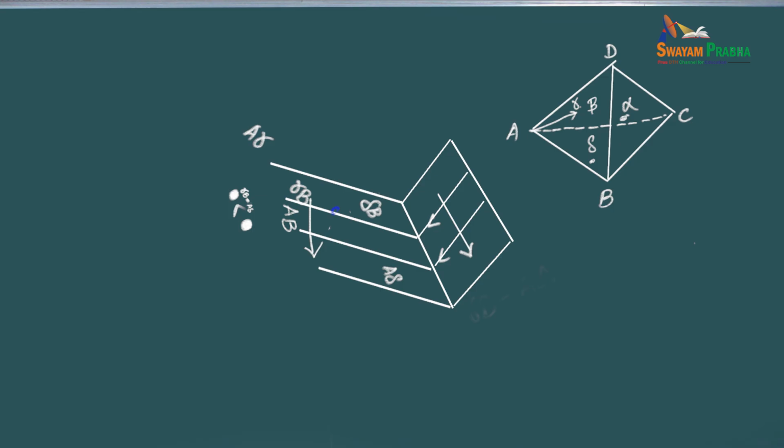And now I have like an electric circuit. I have a Burgers vector coming in. I have a Burgers vector coming out, or I can put it in the other direction. I have a Burgers vector coming in, I have a Burgers vector coming out, and then I have another Burgers vector here coming out. So for the topology, what I need to have is the sum of the three Burgers vectors has to be 0. Yes? And so the Burgers vector that I have here is a net Burgers vector. It's going to be gamma B minus A delta.